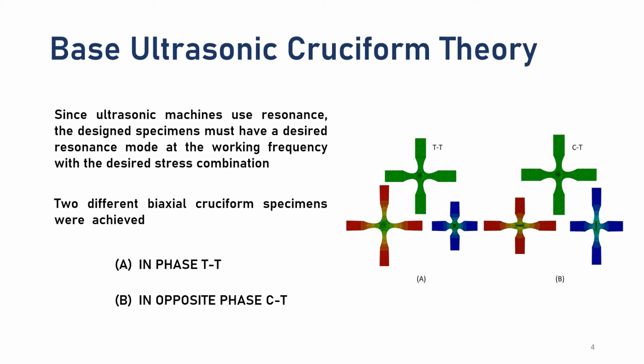Knowing that ultrasonic machines use resonance as a way to achieve the high frequency fatigue, we need to design cruciforms that have a resonance mode at the working frequency and with the desired stress combination at one desired fatigue testing region. So with the modal analysis of cruciform geometries, we were able to achieve two different geometries: the in-phase tension-tension seen here on the left and the out-of-phase compression-tension seen here on the right.